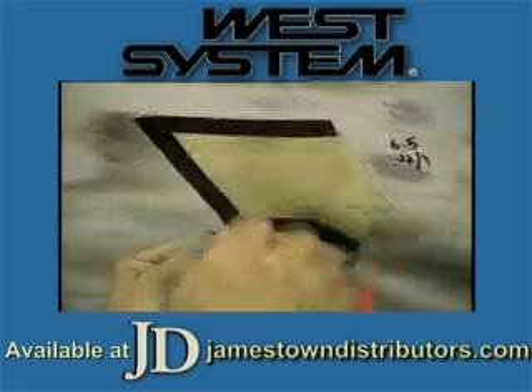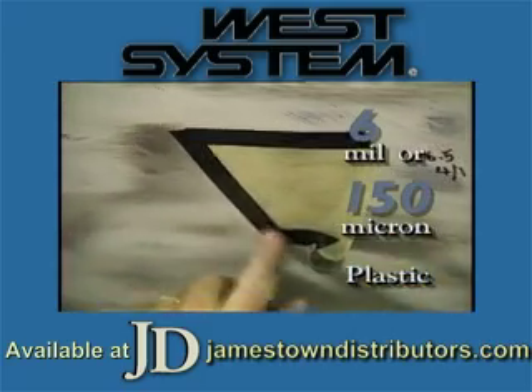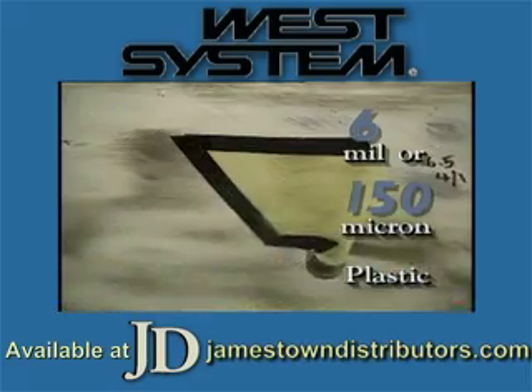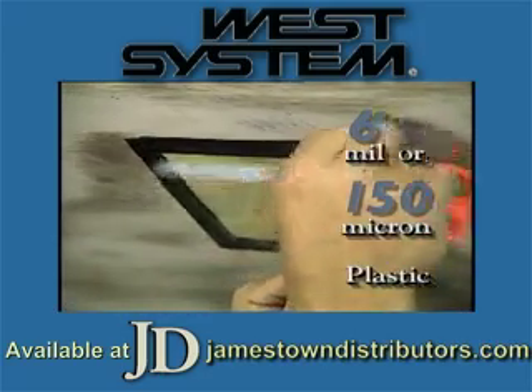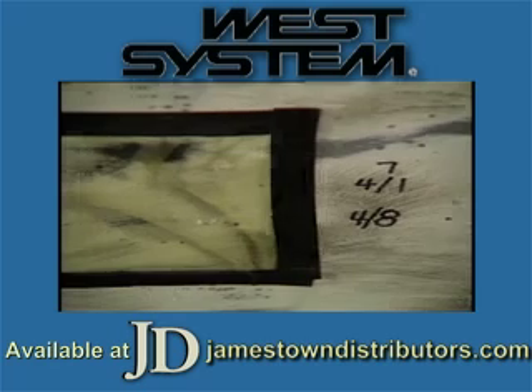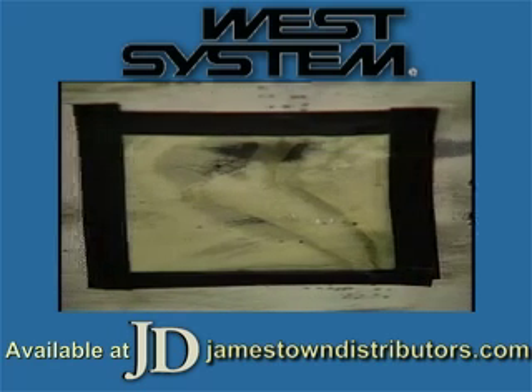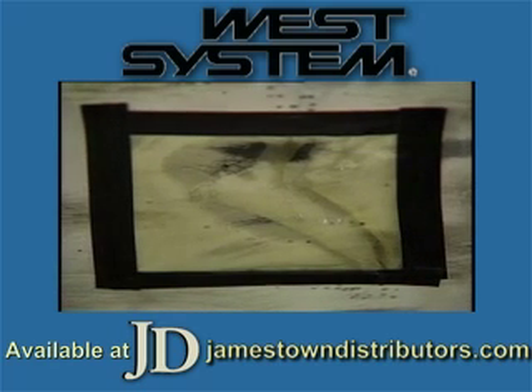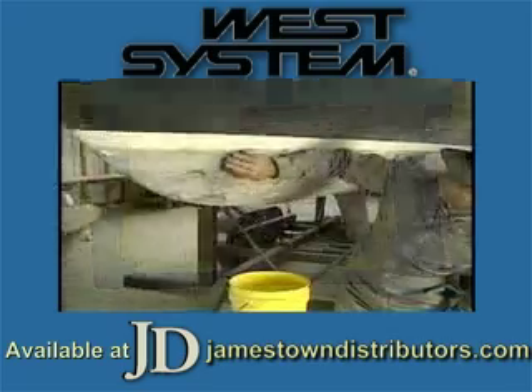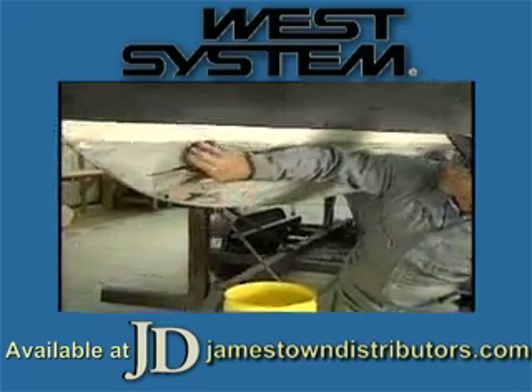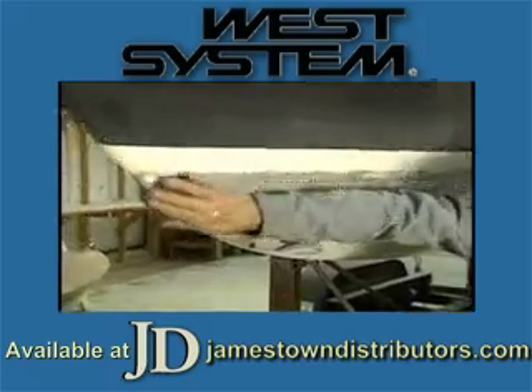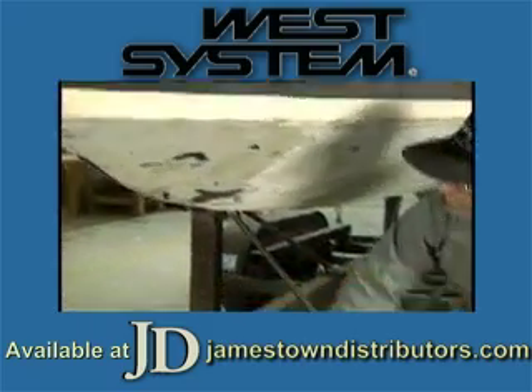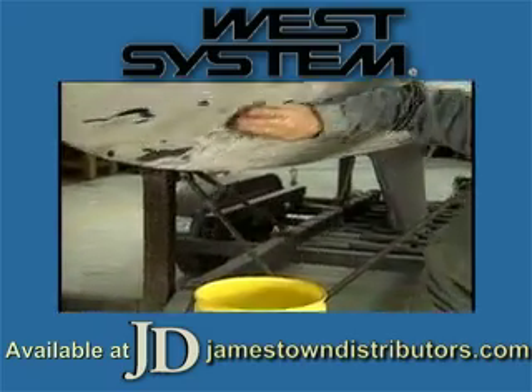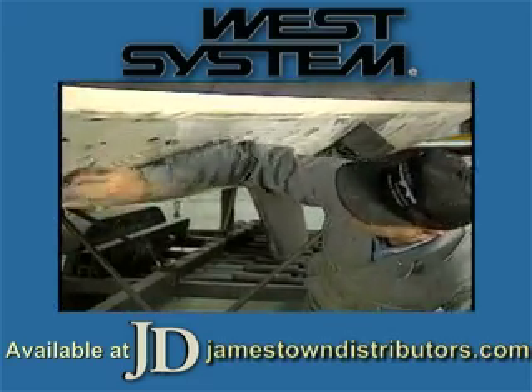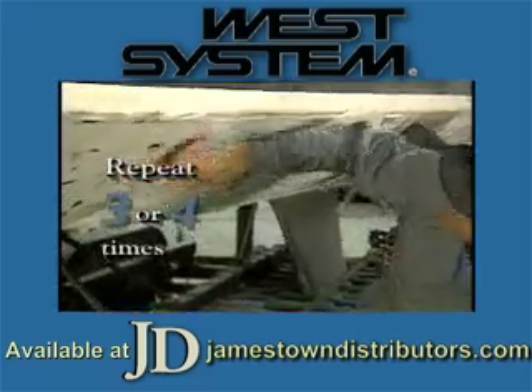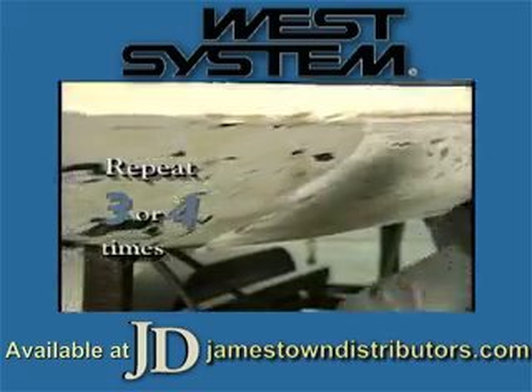For a good backup device, tape 6 mil or 150 micron thick plastic to several locations on the hull with vinyl tape. If the hull is drying relative to ambient humidity, you'll observe condensation on the plastic. After the hull has reached a low moisture reading, you must steam clean or flush it with hot water. Let the hull stand for a day or two, then wash again. Repeat this 3 or 4 times, monitoring the moisture content.